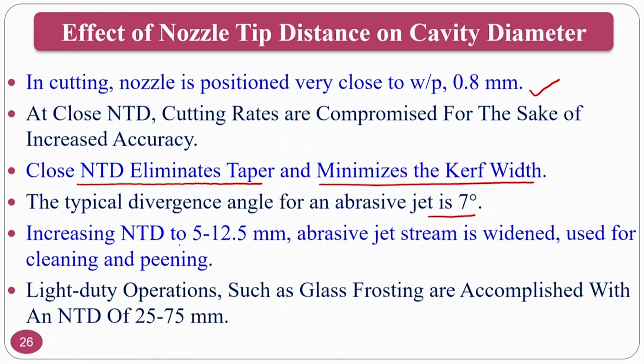If you increase the nozzle tip distance to 5 to 12.5 mm, the abrasive jet stream becomes widened and is used for cleaning and peening applications. That means that at higher distances, it is not going to do the machining operation; however, it is going to do the cleaning operation or the peening operation. The light duty operations such as glass frosting are accomplished with a nozzle tip distance beyond 25 mm. So, whenever you want to do glass frosting and similar things, you go for far away distances beyond 25 mm, so that it will do some texturing on the surface of the glass. Some people who want to take up research areas for texturing of brittle materials can go for the abrasive jet texturing process also.